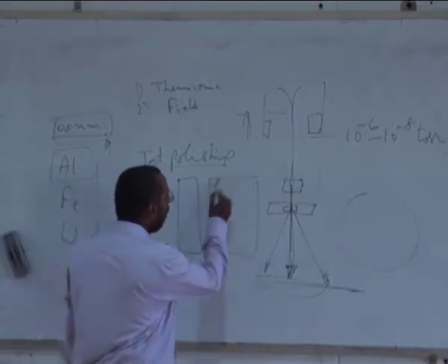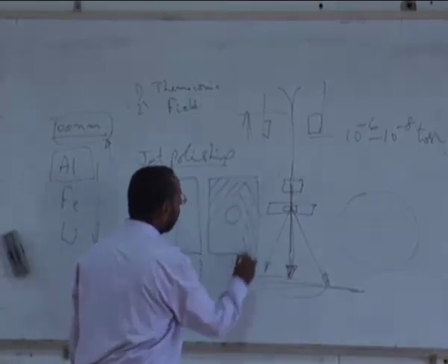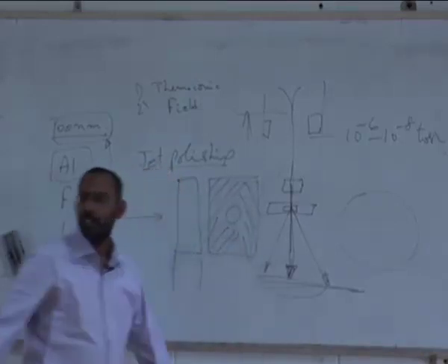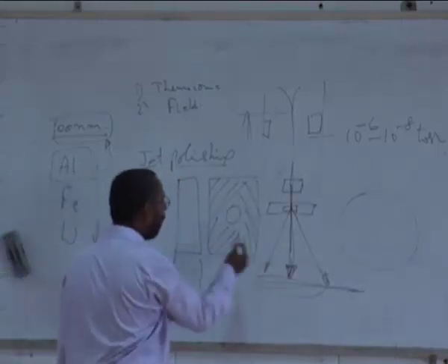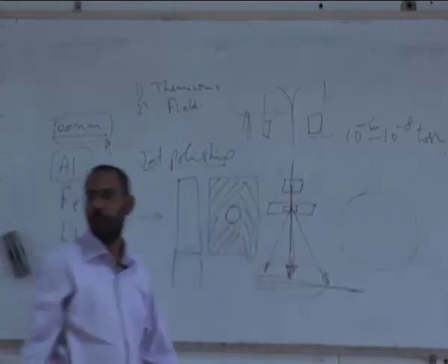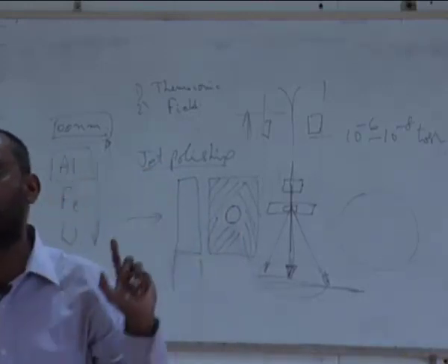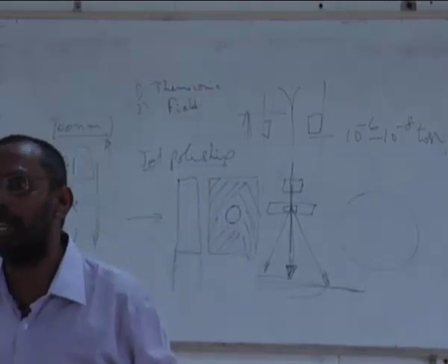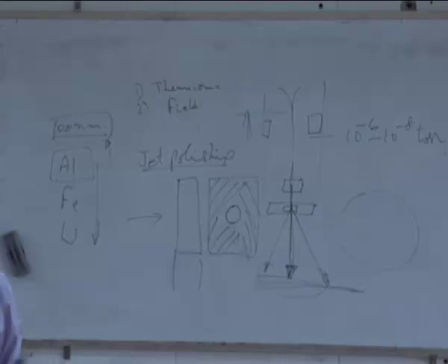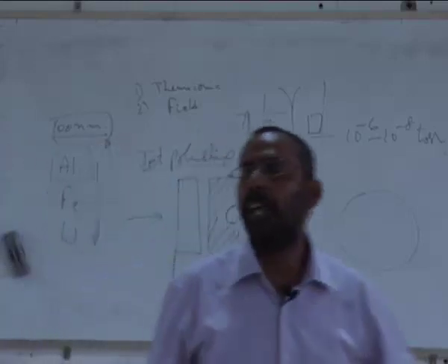I apply a certain non-conducting paint on this, let's say nail polish, for example. Nail polish is non-conducting. I apply nail polish everywhere excepting a small region. I only allow a small region to be opened up. The rest I just paint, and put it into an electrolyte, which is basically nothing but an acid solution.